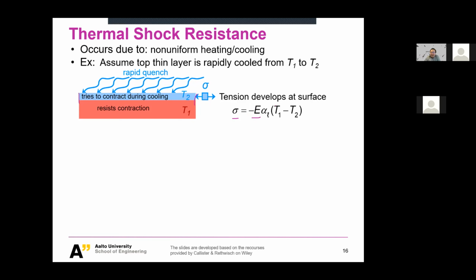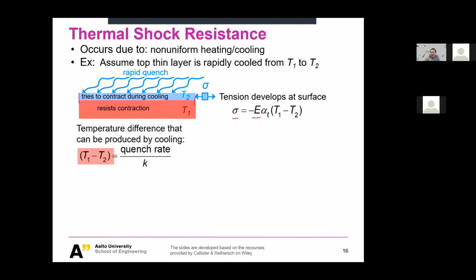Yeah, it is exactly related to the difference of the temperature, right? The T1 minus T2. Because we're talking about relative ones. And how is this temperature related to the process? Maybe you could imagine if we make a very fast quenching, so the temperature change is so fast, the T1 minus T2 will be larger, right? And if it is so slow, if you just think about the dream case, the quenching rate is so small, it's almost isothermal cooling, you would have no difference. So you will not develop any thermal stresses or thermal gradient over there. So that will give nothing.